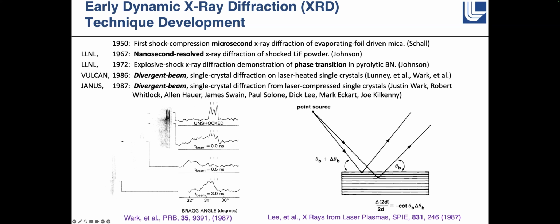But again, these experiments were really hard to do, and so not much happened until 1986, when Justin Wark, who's still a professor at Oxford, still doing similar experiments, again in Rutherford lab and at Janus at Livermore, did a divergent beam single crystal diffraction using laser heated single crystals, and this shows some of his data. And this one was, I believe, on germanium or silicon samples. And the concept of this is that he used a point source.